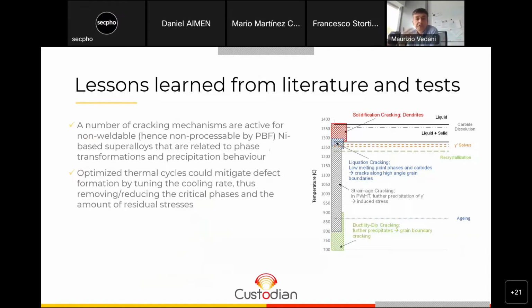What could we learn from that experimental experience, and from the literature, from the theory? There are a number of cracking mechanisms that we have to face and challenge for these alloys that are classified as non-processable in the literature. If we put those cracking mechanisms on a temperature scale, as you can see here on the right-hand side of the slide, the red temperature range refers to solidification cracking. Then, right after having finished the solidification, we have liquation cracking, and then just to recall, we have strain age cracking and ductility dip cracking in the solid stage.